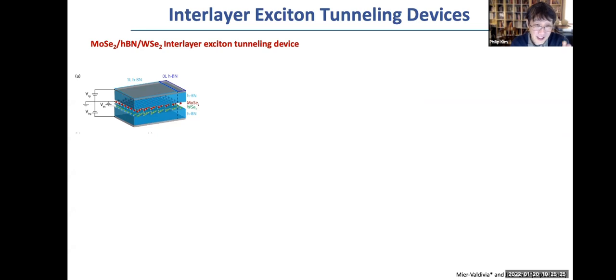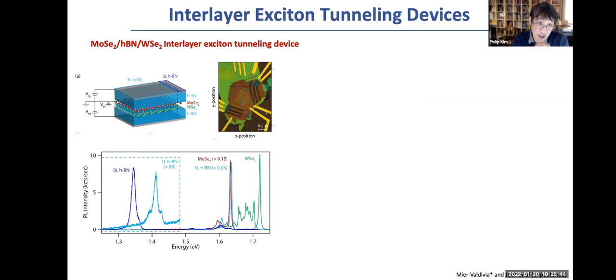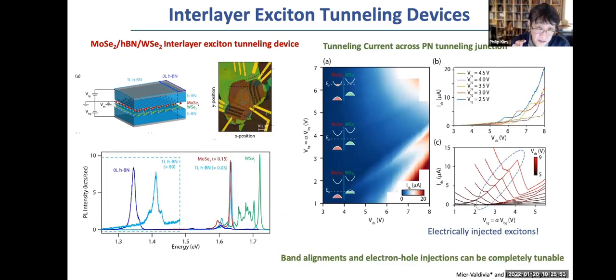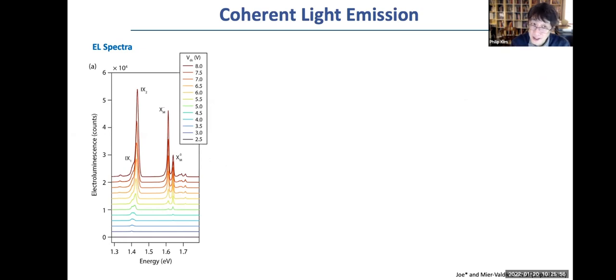But more importantly, now they can also, with a small bias, tunnel back, so the recombination of the electron and hole can be controlled by the bias voltage, and you can get the direct light out from this interlayer exciton. So by just observing the light emission that corresponds to the interlayer excitons, which beautifully shows up in this type of spectrum, and looking at their quantum statistics, you should be able to tell whether there is really quantumness going on.